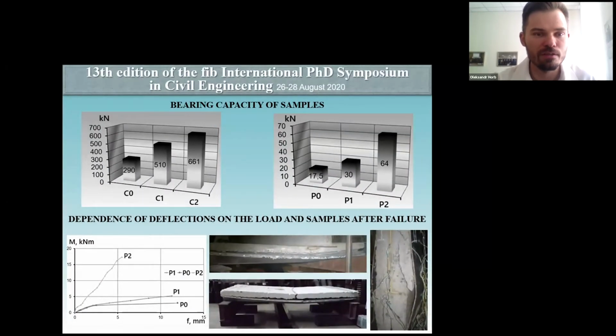As results show us, if we talk about short columns, C0, it's column without glue connection. C1, it's a bearing capacity of column with adhesive without filler, and this is the most useful for such type of connection, type of polymer: one part of acrylic, one part of hardener, and two parts of filler. And the best results we get with this type of glue. In plates, we can see that